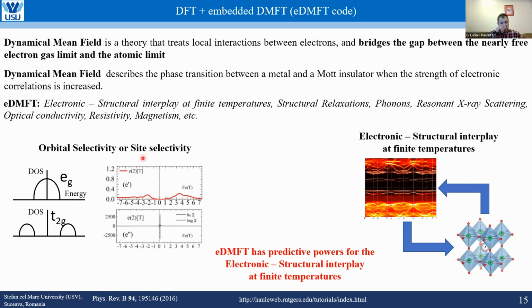Now, one interesting thing here is that I can have a metallic state which is weakly correlated or strongly correlated, but you can also have an insulating state. The insulating state can be opened due to correlation. So I have one orbital occupied by one electron, and it takes a lot of energy to bring in the other one, thus I'm opening the Mott gap.